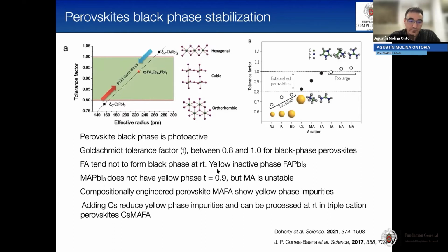Further, we can engineer the composition of the perovskite just by adding different amounts of mixed cations. For example, using methylammonium and formamidinium, we reduce the amount of yellow phase impurity. And by adding another cation, such as cesium, we reduce these impurities further, and we can process this at room temperature, like a triple cation perovskite, which is nowadays the state of the art.